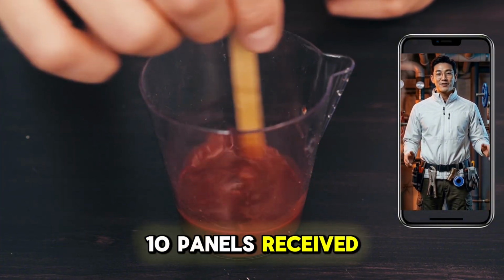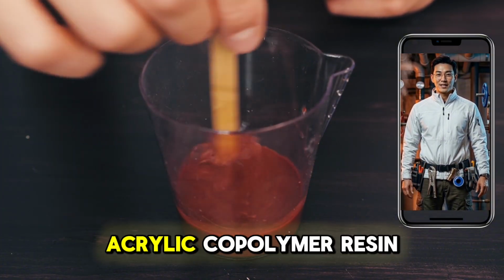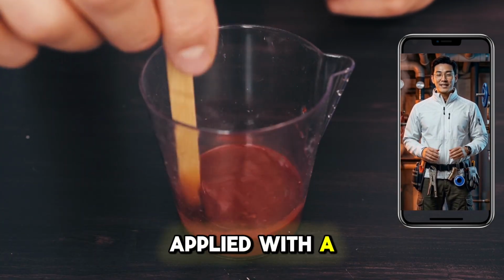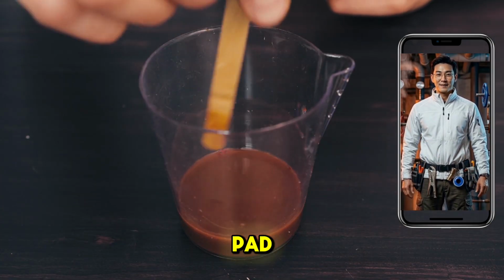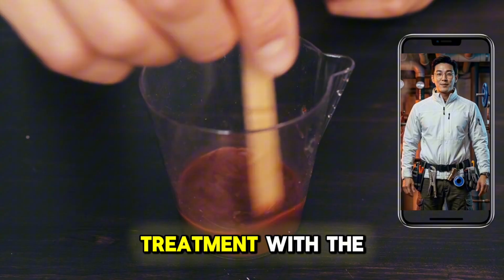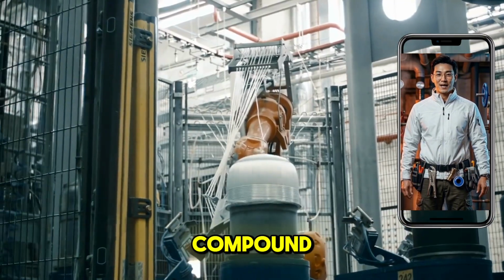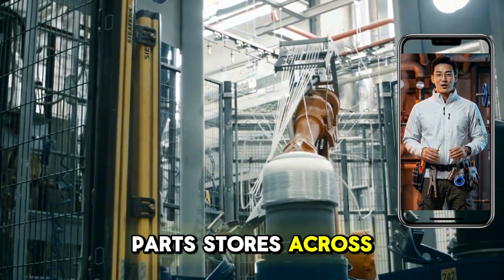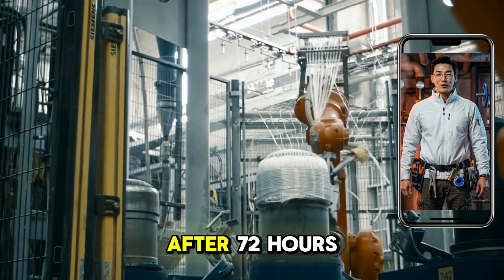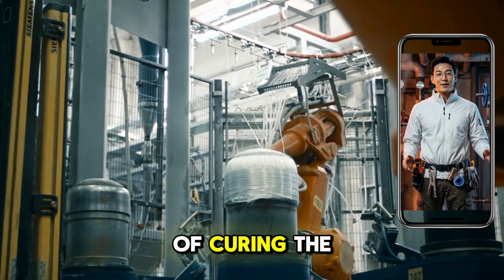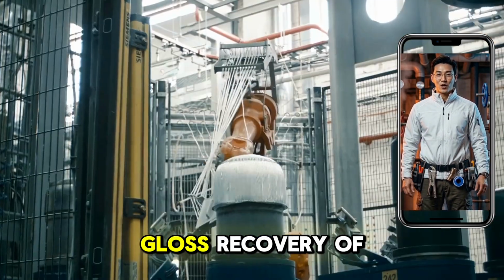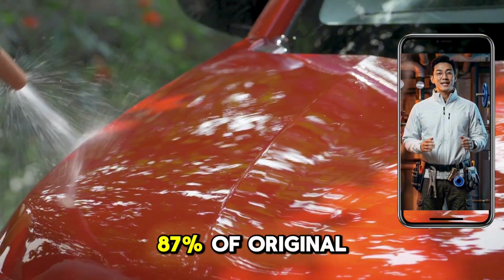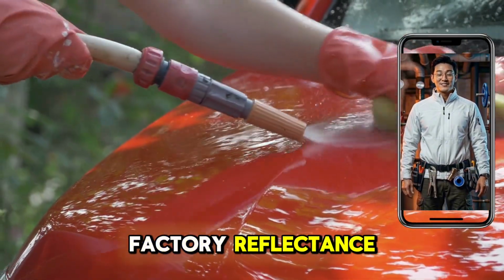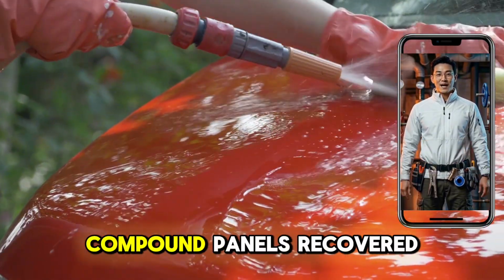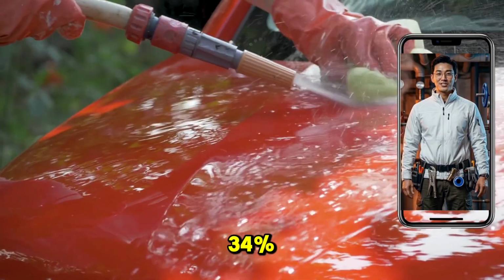10 panels received a single coat of diluted acrylic copolymer resin applied with a standard foam applicator pad. The other 10 received treatment with the leading commercial rubbing compound sold at auto parts stores across the United States. After 72 hours of curing, the resin-treated panels showed gloss recovery of 87% of original factory reflectance values. The rubbing compound panels recovered 34%.